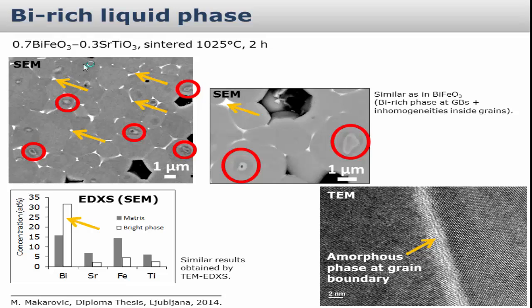And this is an example of the same ceramic that was X-ray diffraction pure, seen on a microscope with a backscattered image that's sensitive to the phase composition. We see a situation classical for diffusion-controlled reaction, where you have a phase at the grain boundary and a certain inhomogeneity inside the grains, very similar to BiFeO3. EDS shows that this phase is basically a bismuth-rich phase. And TEM confirmed that the phase is amorphous, so it's a liquid phase.